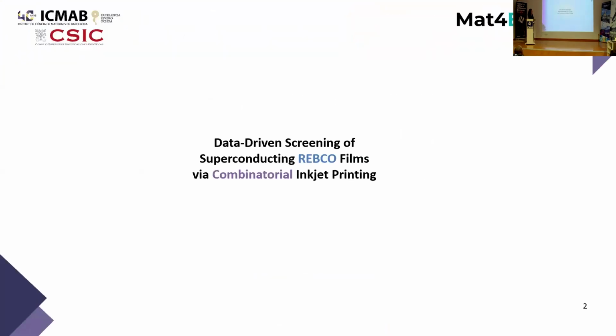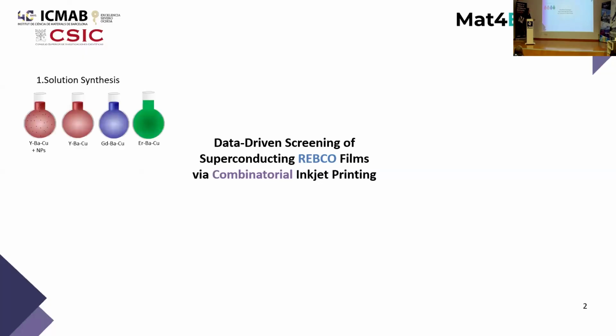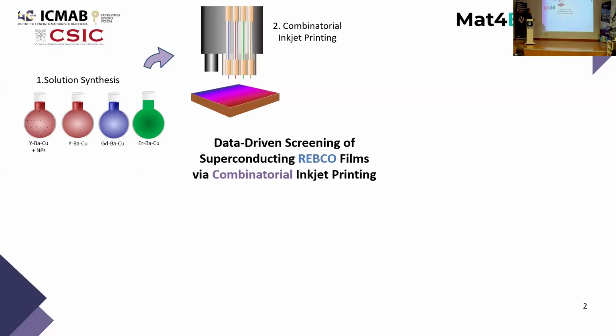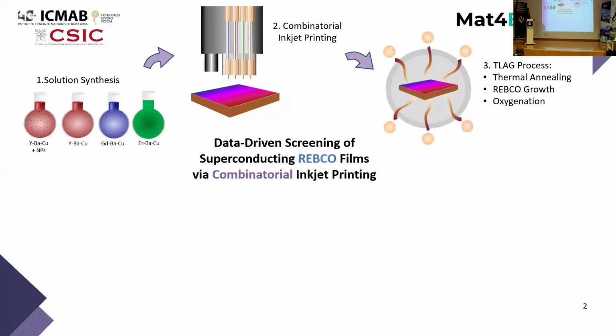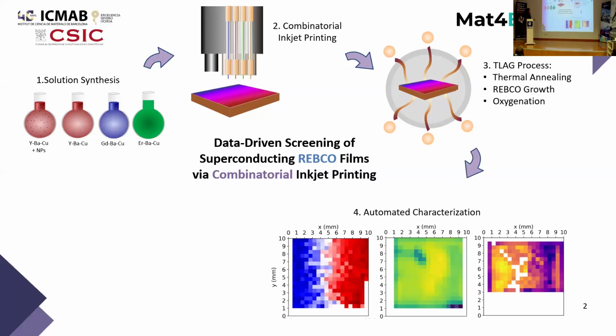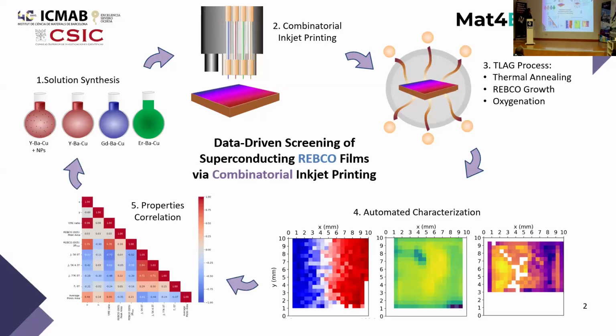So the outline of my presentation basically consists of the 5 steps that we perform to fast screen the REBCO films. First of all, we synthesize precursor solutions with different rare earths that we then use as ink in an inkjet printer to deposit combinatorial samples. Afterwards, we grow these samples through the TLAG process in order to produce the REBCO film. And finally, we can perform a series of automated characterization techniques in order to build a large data set and to finally optimize the final material.